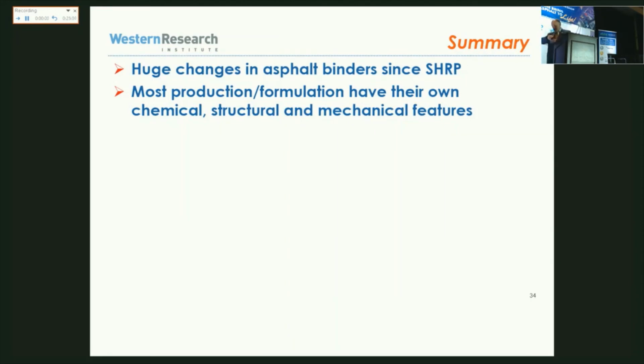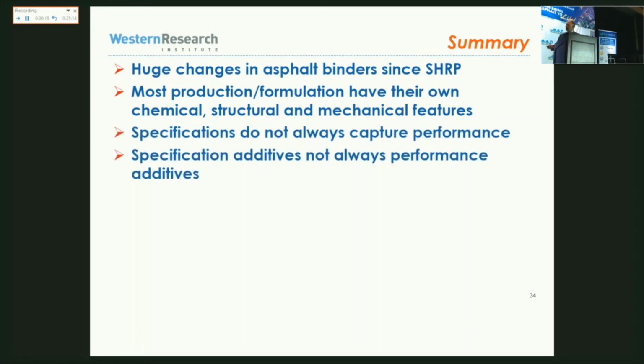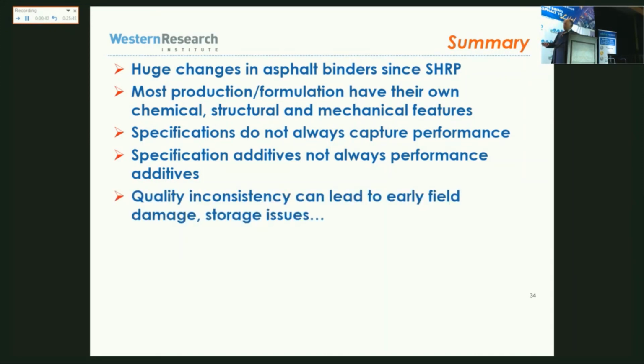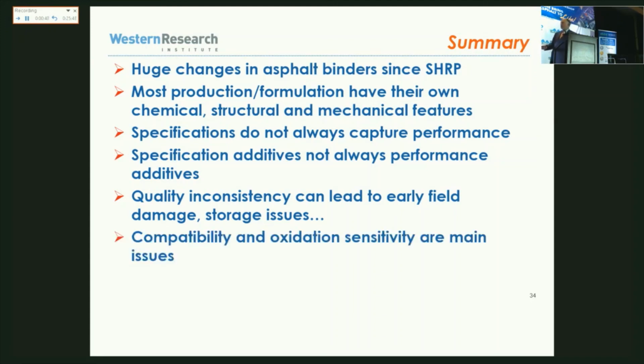So I'm kind of late, but in summary, there have been huge changes in asphalt binders since SHRP. Most productions and formulations have their own chemical structure and mechanical features, so we can fingerprint them. Specifications do not always capture performance, and I'm referring to the Superpave specs and some new parameters. Specification additives are not always performance additives, because you can pass a spec because of an additive, but if the spec is not good, then you can fail in terms of performance. Quality inconsistency can lead to early field damage. Also, storage issue, I didn't talk about it, but that's, of course, a very important point.